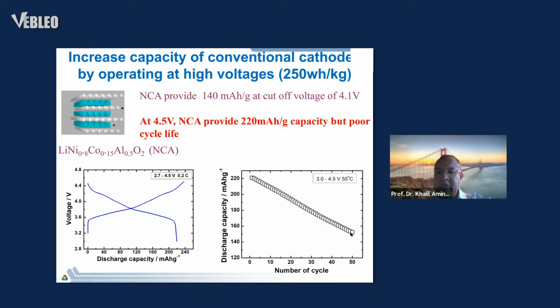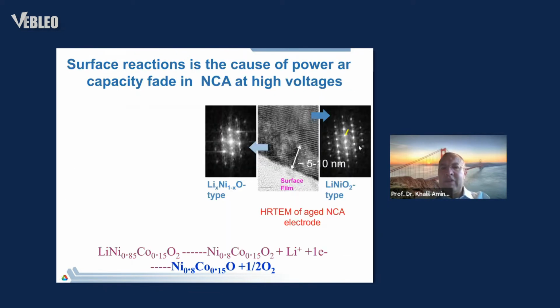So at Argonne, what we did, we took particles from an electrode at the end of life, and then we microtomed them in half and looked at them by high resolution electron microscopy. And this is what you get. You get the layered structure, as you can see. But then you have another phase that, through electron diffraction, is actually a nickel oxide phase, which is very, very resistive, not permeable to lithium if you want. And we have a surface film as well.